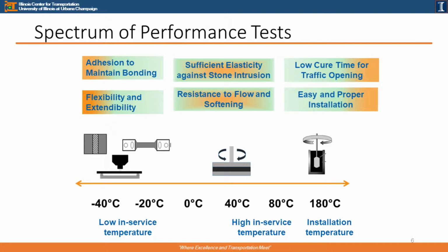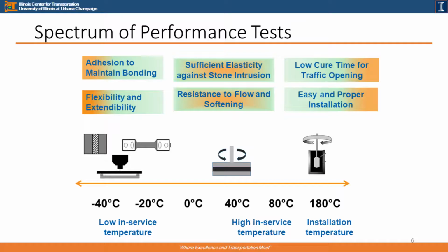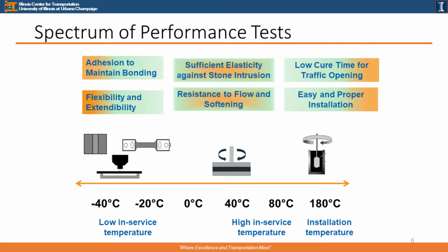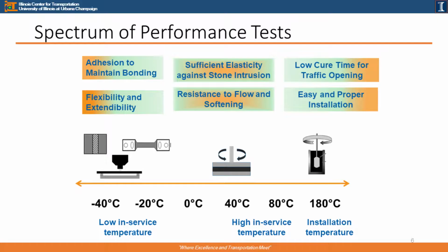So let's talk about the spectrum of performance tests. The first thing is you have to install sealant properly, and the temperature will be about 180 degrees Celsius. When you install the sealant, what property do we have to know? The first thing is low cure time for traffic opening, and also easy and proper installation. After installation, the sealant will be used at high temperatures, such as 40 to 80 degrees Celsius. And also in winter time, it will be served at minus 20 to minus 40 degrees Celsius.